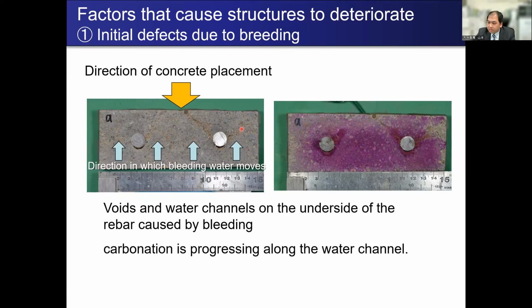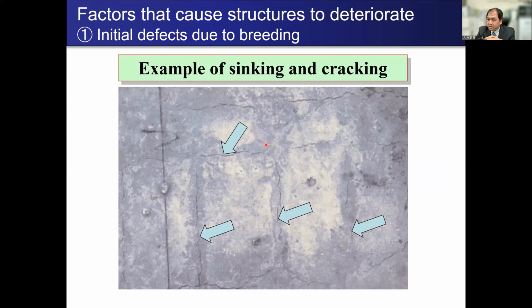This is a water channel, and along this water channel, the carbonation proceeded. And this is the sinking crack from the surface of the concrete. You can see the cracks along the rebar. This is a sinking crack. This is also due to the large amount of bleeding.